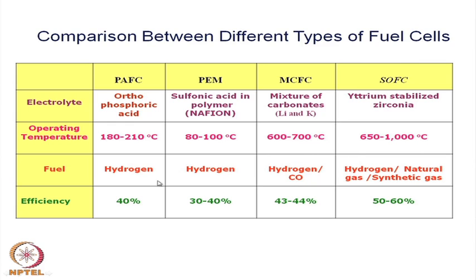Actually, when people started using solid oxide fuel cell, the temperature of operation was quite high, about 900 to 1000 degrees centigrade. And so, because of various kinds of research and the invention or discovery of different materials, or development of different materials, the temperature is coming down slowly. Currently, it is about 650 to about 800 degrees centigrade, mostly 800 is the limit now. Still, research is going on whether the temperature can be further lowered to about 500 to 400 degrees centigrade.